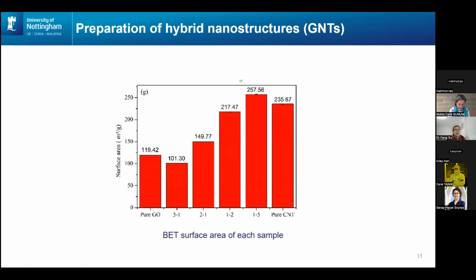We also would like to check how well the dispersion is. So we use BET to measure the surface area for each sample. From left to right, we started to add carbon nanotubes into pure graphene oxide. This is 5:1, one portion of carbon nanotube into five portions of graphene oxide. We keep adding carbon nanotubes, and then the last sample is pure carbon nanotube.